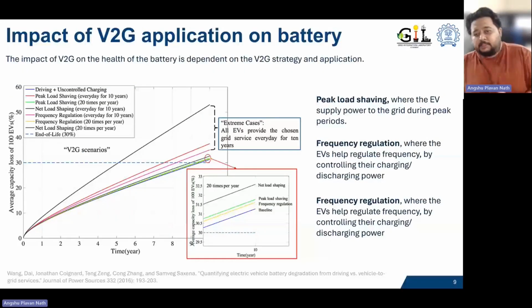Now, depending on V2G applications, your impact on the battery degradation will be different. So in this paper, they took 3 different services: peak load shaving, frequency regulation, and net load shaping. Net load shaping was the most strenuous exercise. So if you see here, the baseline is where there was no vehicle to grid service. Now, if we add frequency regulation on top of it, the degradation increased by around 1.5%. If we add peak load shaving, around 1.7%. If it is net load shaping, the degradation increased by around 2%. So the impact of V2G on your degradation of the battery is quite minimal.